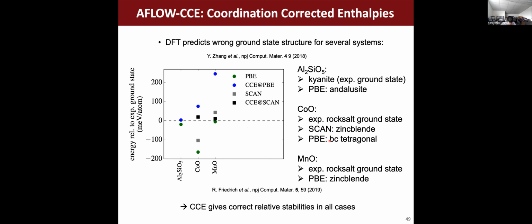An important part of these corrections is that it's important that we not only reduce our errors, but we do so in a way that is consistent for the ordering of polymorphs. Okay, so it's not only important that you just reduce the errors, but that you reduce the errors so that the system that should be the ground state appears to be the ground state. So we did this analysis for 3 systems here where we know what the ground state should be from experiment. Okay, and we know what PBE gives us as the ground state, which is going to differ from the experiment. And we can show that for these 3 systems, especially as we use SCAN. SCAN is a particular functional. It's a little more expensive than, let's say, raw PBE, but it's going to give us better results. If we use our corrections with SCAN, we can actually recover back what the experimental ground state should be. Okay, and so even in the relative sorting of polymorphs, we can get back what we expect to be the ground state.